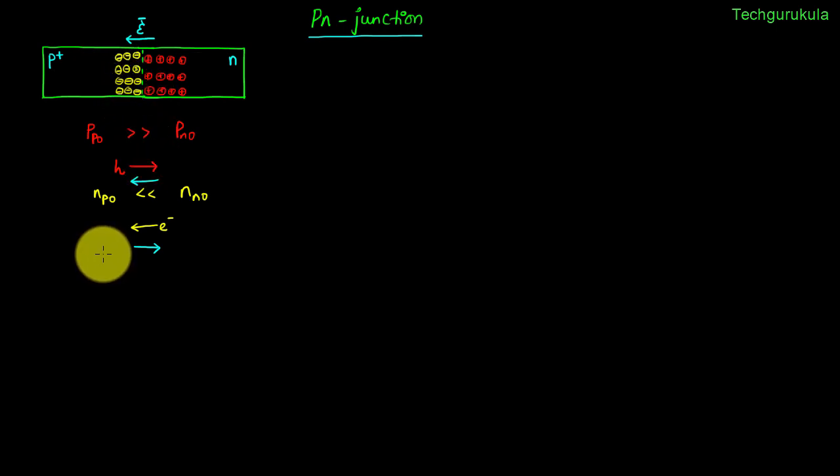And now we can say that the p-n junction has reached equilibrium state, where there is no net current flowing through the p-n junction. But we cannot say that individual currents are zero. As electric field is present, there is drift current, but the net current is zero, which means there is a diffusion current in the opposite direction, balancing exactly. So there is diffusion current and drift current in the p-n junction. They are balancing out each other exactly, so that we don't see a net current flowing because we didn't apply any potential difference.